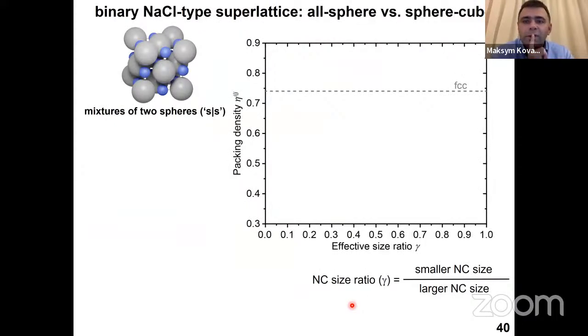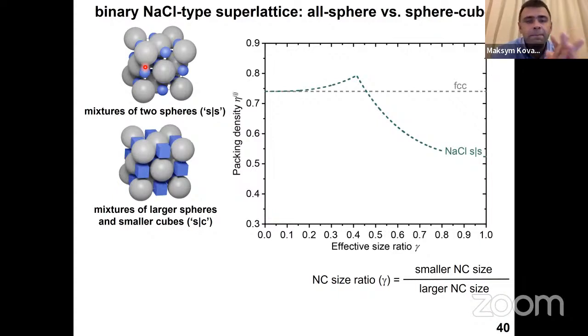And then we thought, okay, this lattice is known for spheres. Can we make it out of cubes? And now the rule of thumb here is the following, that you need to mix the sizes of your spheres, or a cube plus sphere, in a certain range where the resulting packing density for this lattice will be the highest. Because unlike two atoms where you cannot really change the size, here you can.